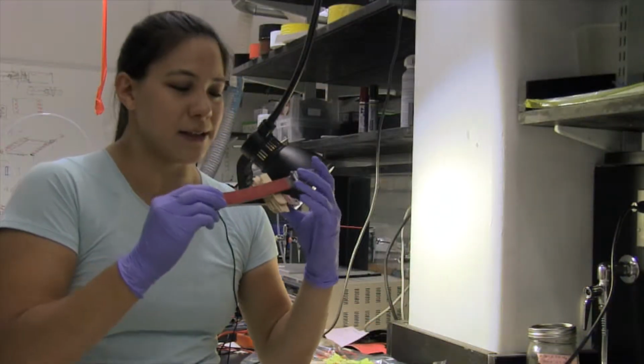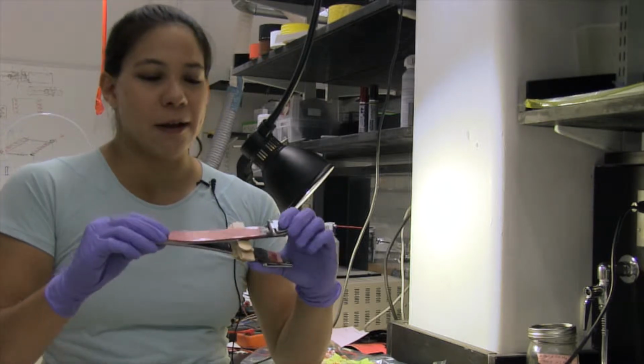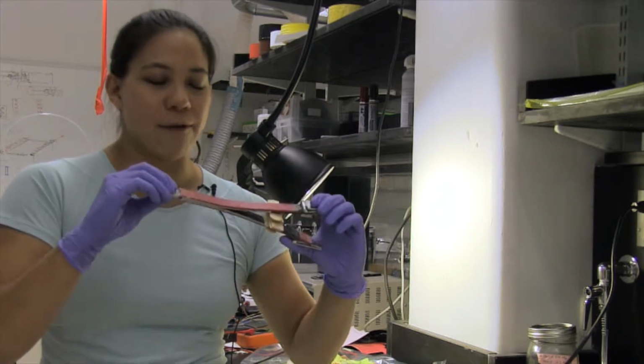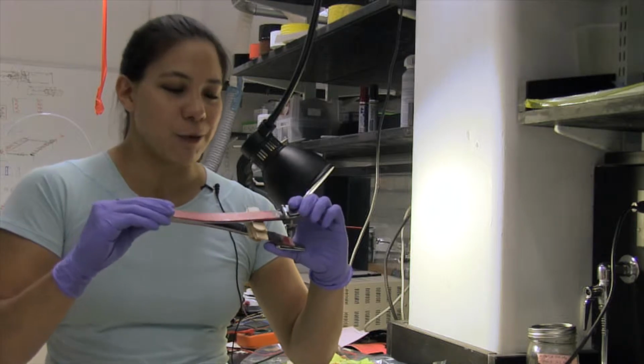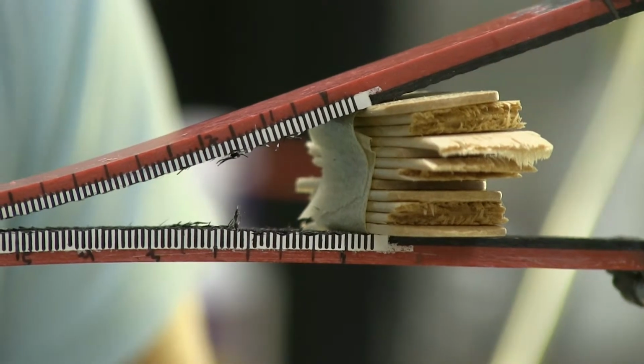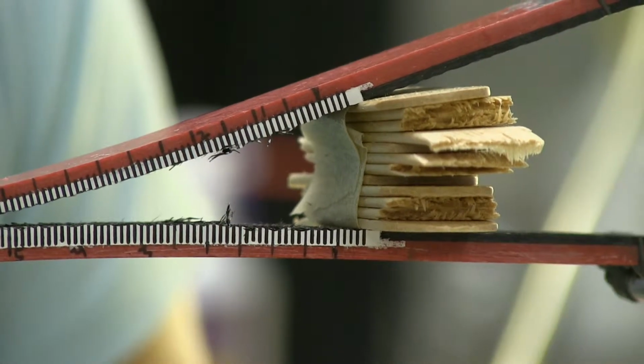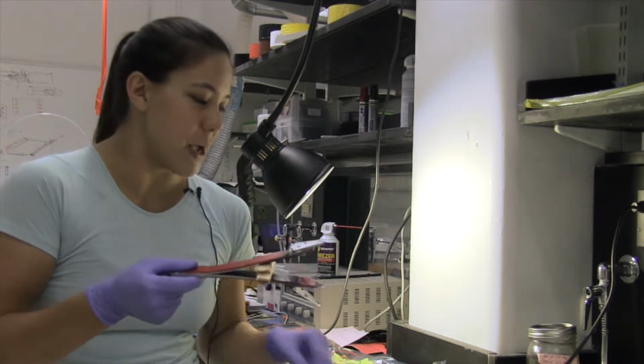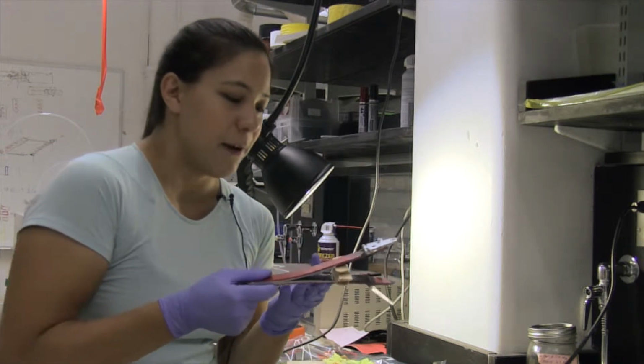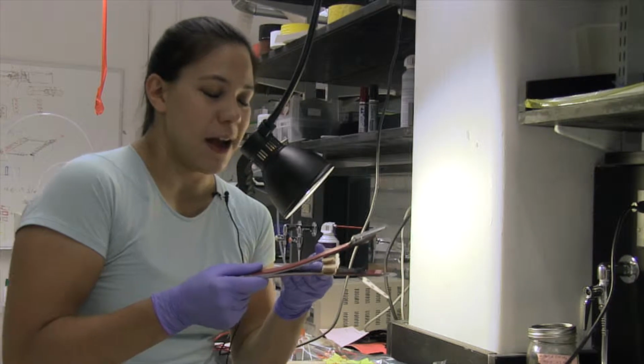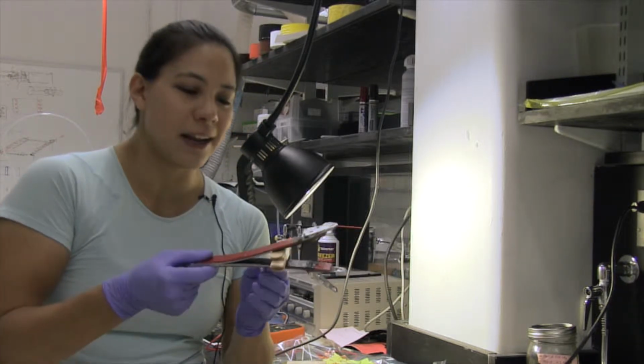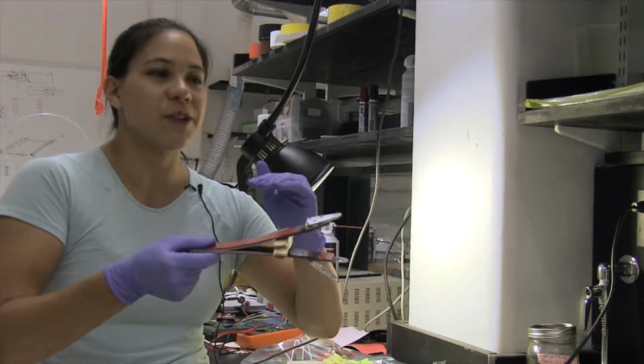In this particular case, we're trying to propagate the crack between the middle two layers. This is made up of 8 layers, and so we're trying to propagate the crack between layers 4 and 5. Because of how the nanotubes were toughening that interface and how the plies were nesting, that interface was too strong for the crack to propagate and actually jumped 1 layer over to a weaker interface.